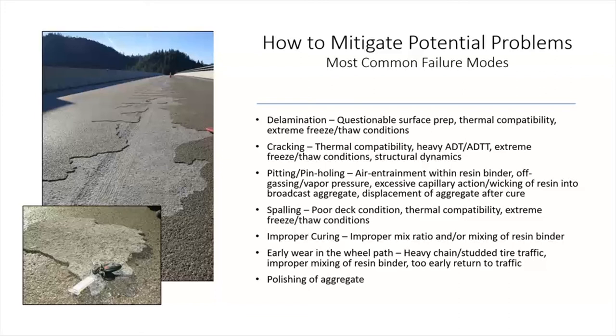These overlays work really well and they last a long time. So I want to talk about when you're considering a thin bonded overlay, how do you make sure it's on a deck that's in good condition? How do you make sure that you have a good specification? How do you make sure you got a contractor that's going to do it properly? Because things like cracking, delamination, pitting, pinholing, spalling, improper curing, early wear, and the polishing of the aggregate, those are all things that can go wrong. And we don't want those things to happen. And if you make the right decisions, they won't happen.